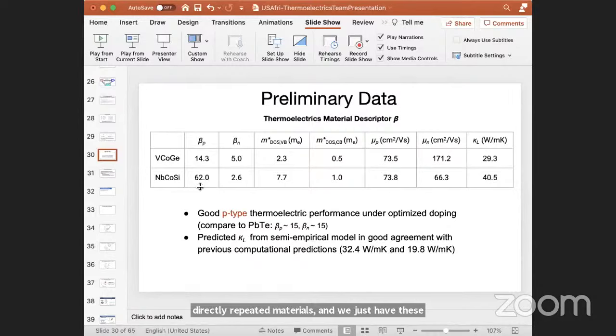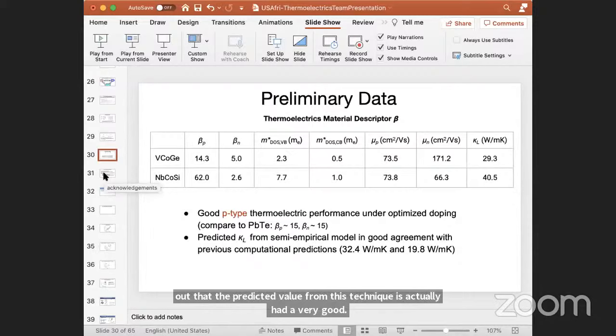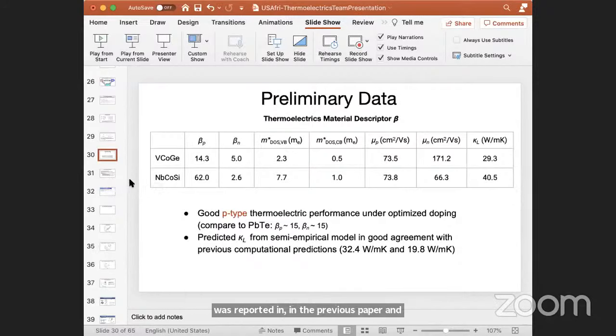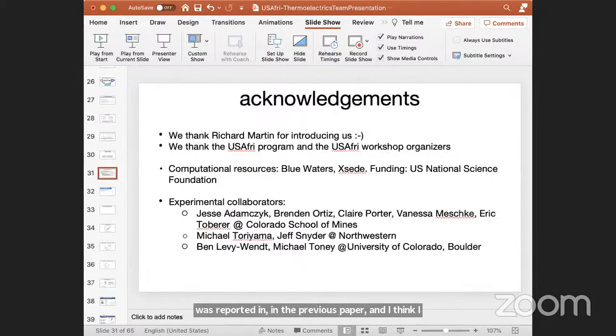We also have this data for our system: the density of states effective mass, in the third column, for the valence band, and for the conduction band in the fifth column. Then we have the carrier concentration, and we found that the value predicted from these techniques has very good agreement with what was reported in the previous paper. And I think I have to pass to Elif to give a word of thanks for bringing us together for these collaborations.